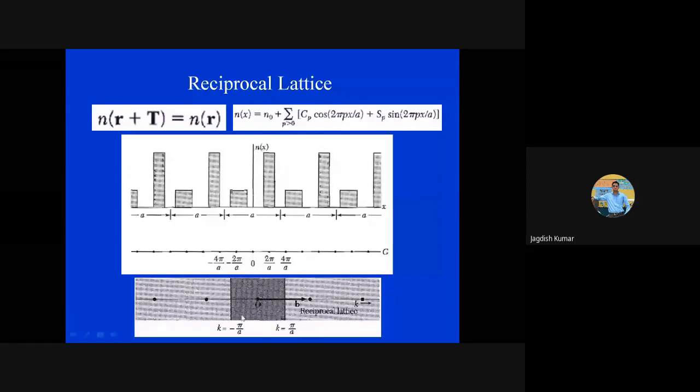How we construct Wigner-Seitz cell or the primitive cell, we take any lattice point as the reference, then connect it to its neighboring points. So we are connecting this one with this point, and then take a perpendicular bisector. So here the length between these points is 2 pi by a. So by what length will the perpendicular bisectors be passing? By pi by a, plus pi by a. Similarly, to the other side, to the left hand side, there is a lattice point sitting at a distance of minus 2 pi by a. So where is the perpendicular bisector sitting? This is sitting at minus pi by a.